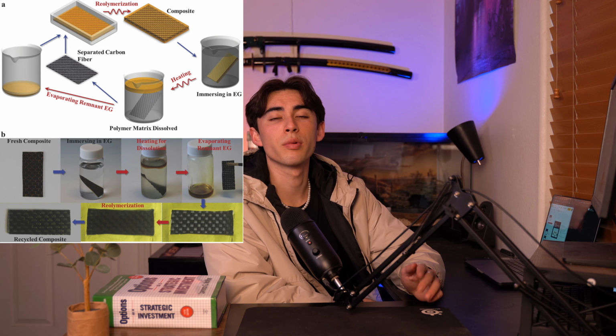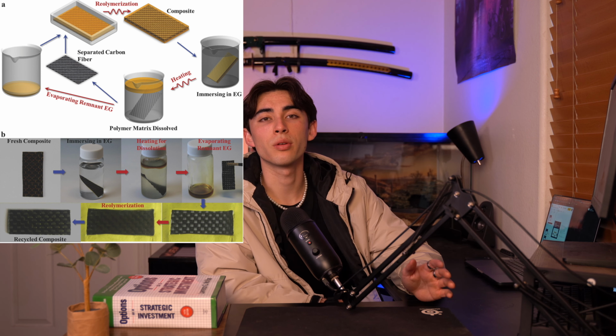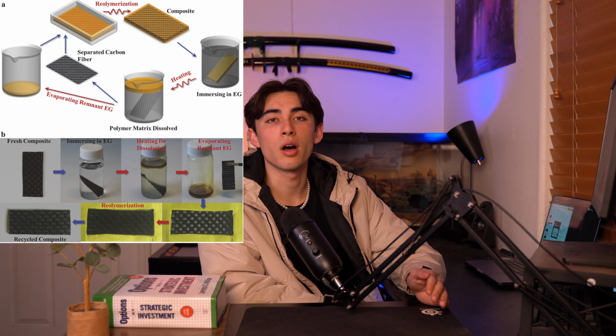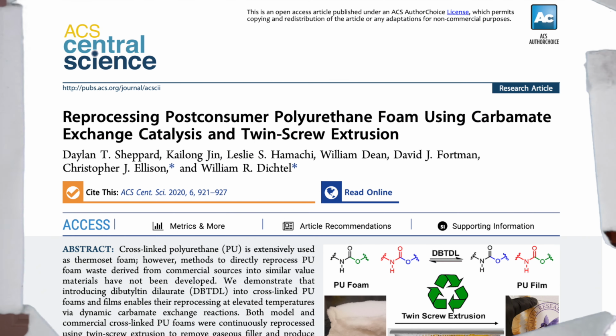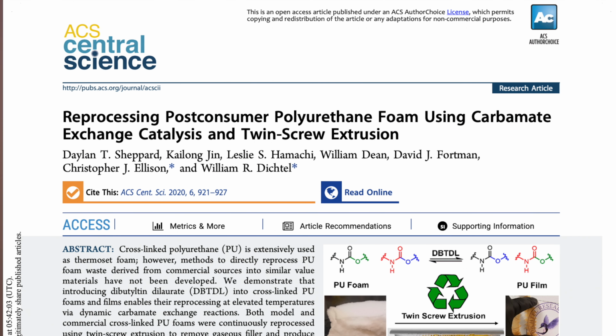The result of this study was clean carbon fibers with nearly 100% recyclability and mechanical strength, and an epoxy that was able to repolymerize. This ultimately leads to a sustainable way to recycle carbon fibers, which is a highly expensive material. Another study by Ellison and associates looked into using covalent adaptable networks in polyurethane foams.